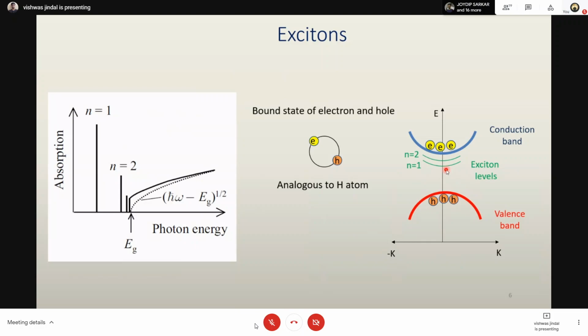When you're talking about excitons, you don't talk about the conduction band and valence band. It's wrong to say where their energy positions are. They cannot form without a gap, and they will form only if there is a gap, that is true. But you cannot assign them a position. Then will the exciton energy levels be close to the valence band or to the conduction band? That is something that is wrong to say, because when you're talking about the valence band and conduction band, you are talking in the one-particle picture.